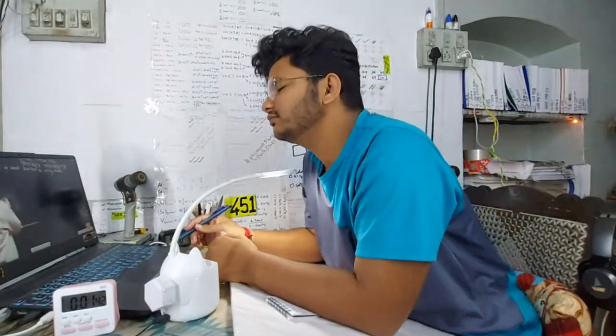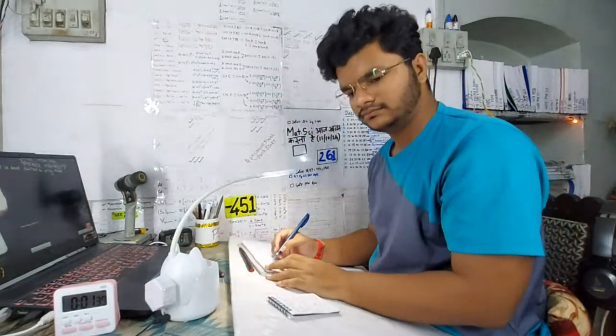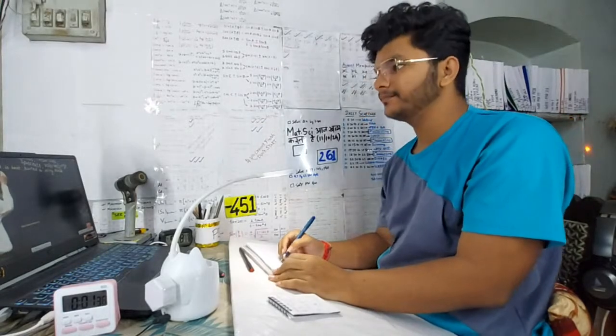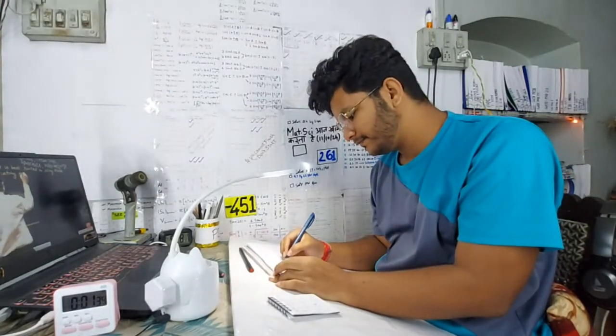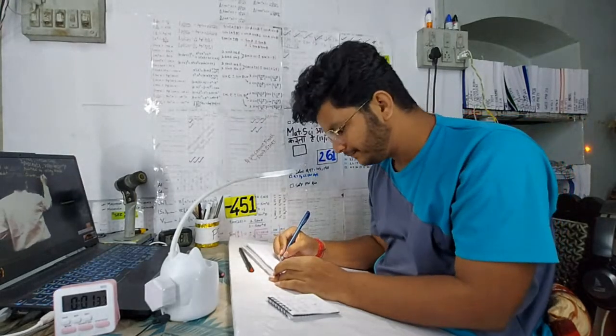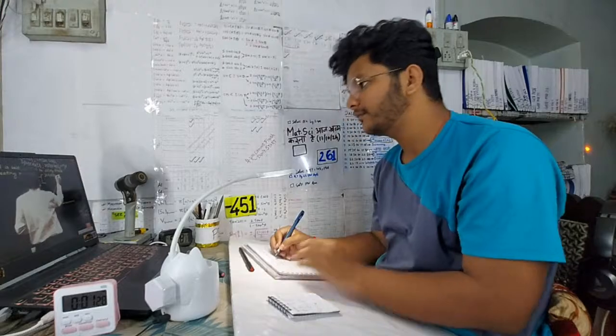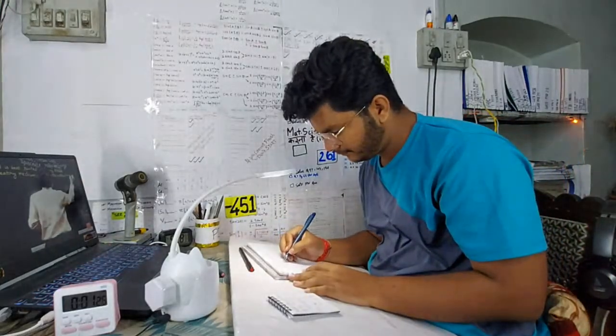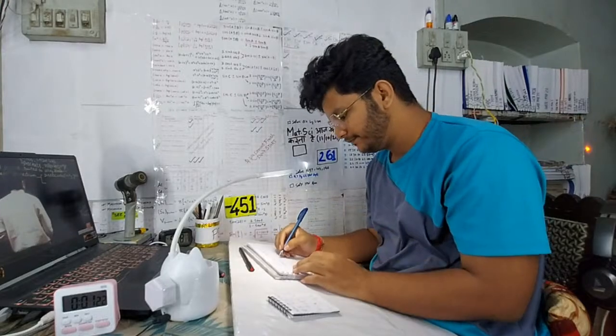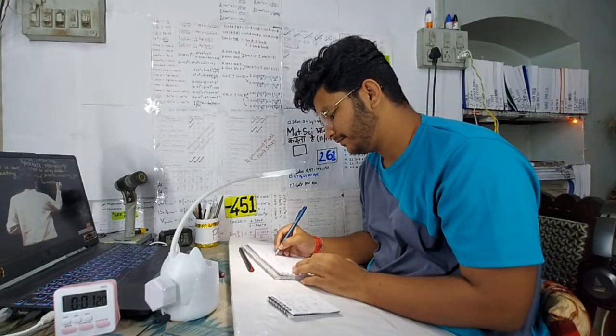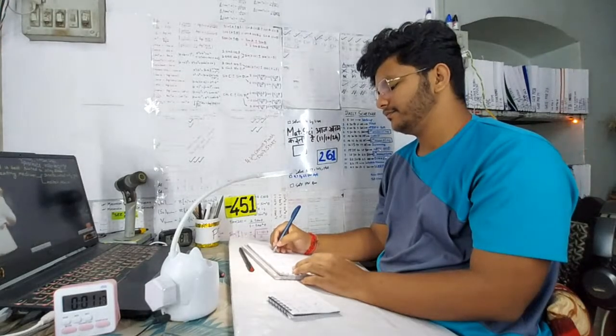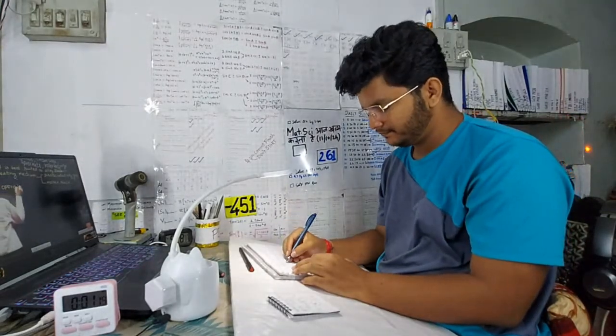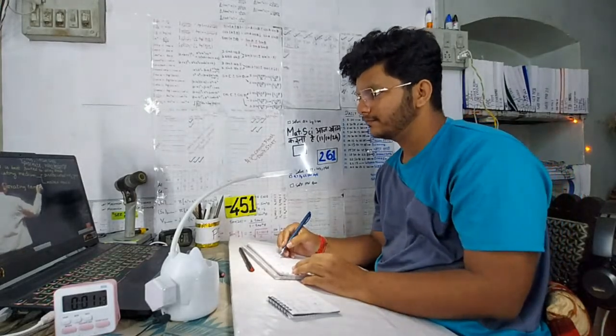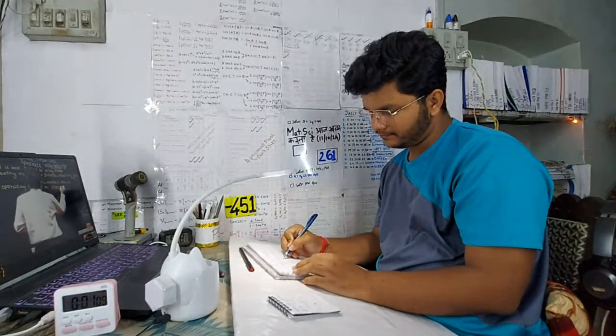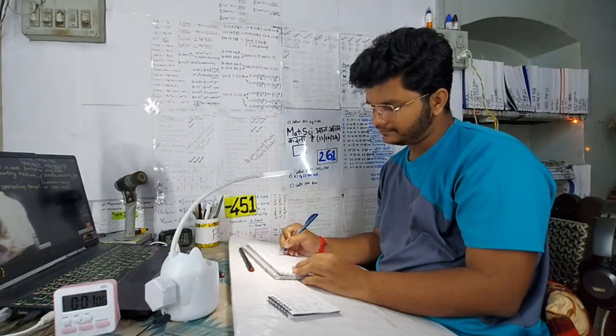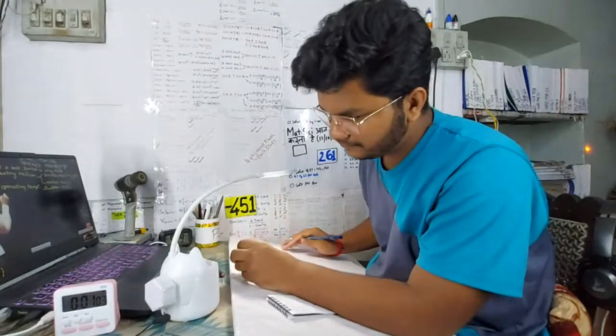So we write these important points here. It is best suited for alloy steels. Next, heating is done. The heating medium can be either dissociated ammonia gas or molten sodium cyanide salt. We write here, operating temperature is 500 to 550 degrees centigrade. No quenching is needed.